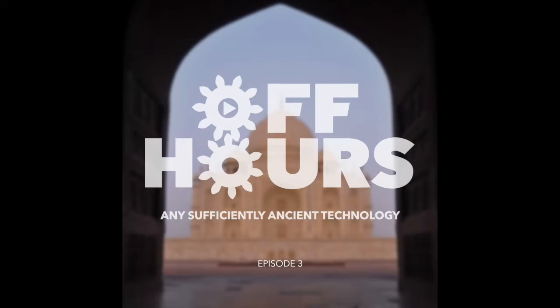It's sitting there inert. And so in the case of my setup, I have a casting machine with a crucible at the top that heats the metal. It has a graphite crucible, so the graphite can handle the temperatures we're talking about. There's a graphite plug that sits in the bottom of it. Below the crucible is the chamber with the flask in it. I use a vacuum pump to draw the oxygen and the atmosphere out of there. Between gravity and the vacuum, when I pull the plug on the bottom of the crucible, the metal then goes tumbling down into the flask. Gravity obviously pulls it down, and then the vacuum also pulls it down, and it pulls any gas or any atmosphere out of that flask.